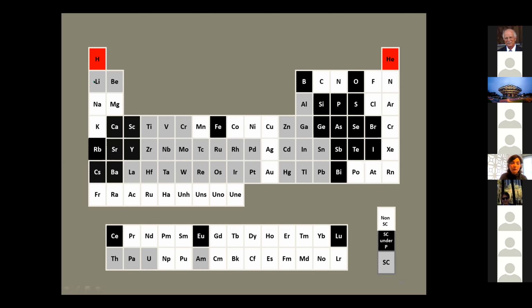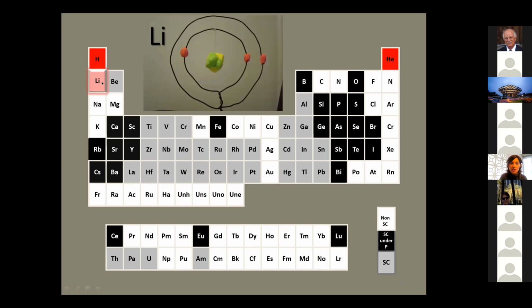On the other hand, if we go to the third lightest element, which is lithium, this is already a metal, and it's super light. I mean, if you compare, for example, lithium-6, which is one of the stable isotopes of lithium, you can see that it's not that much heavier than helium-4, which is a known quantum solid. And basically, the idea is that the interactions are different. I'm oversimplifying everything, but lithium is a good case for looking at this.